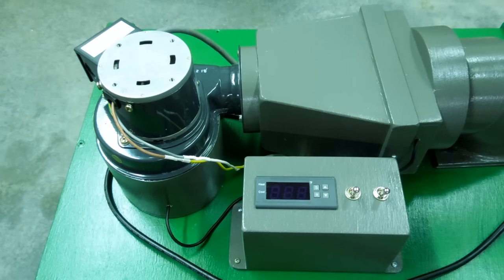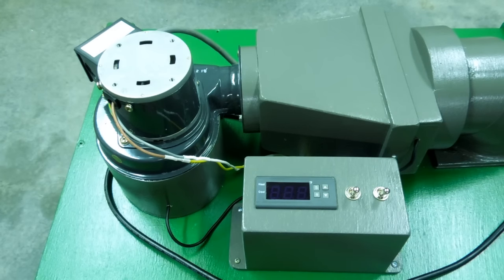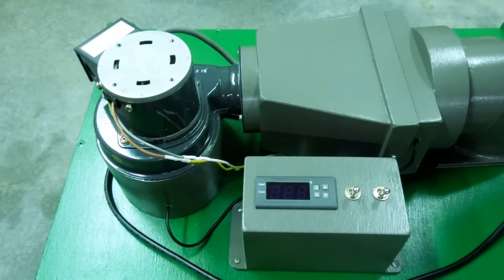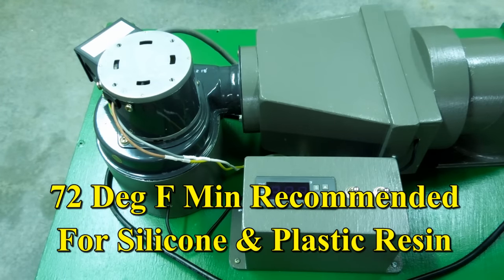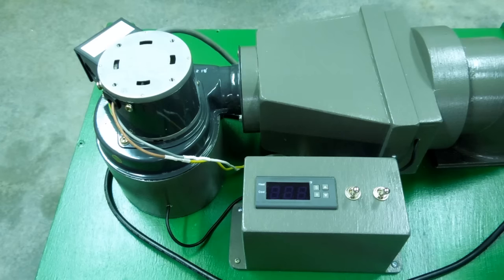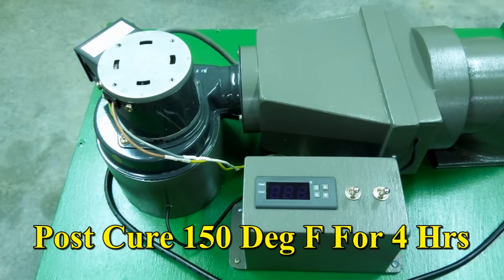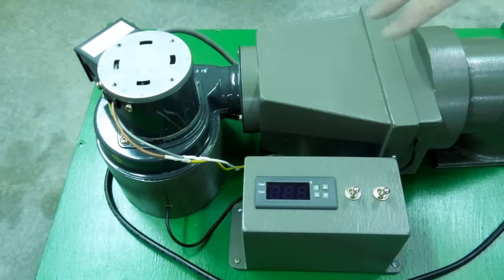There were a couple of reasons for building this. My shop in the wintertime is only heated to 62, 65 degrees, and that's really too cool for these two-part chemicals to react and cure properly. I can put the chemicals in here and set the temperature for 95 or 100 degrees, preheat those chemicals, and then mix them, put them in the pressure pot, put the pressure pot in here, and then the resin castings, and that should cure okay. I haven't had too much problem with the silicone, but the resin, it wants to be warmer to cure properly. And then when you're done, you can put your silicone molds or your resin castings in here and do a post-cure, which is 150 degrees for 4 hours.